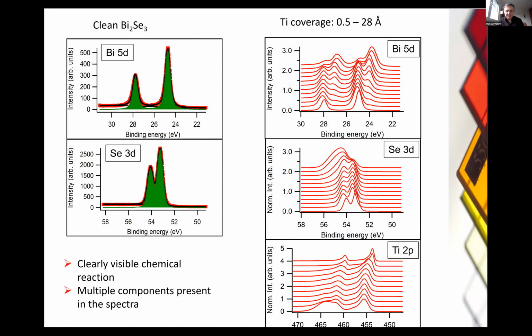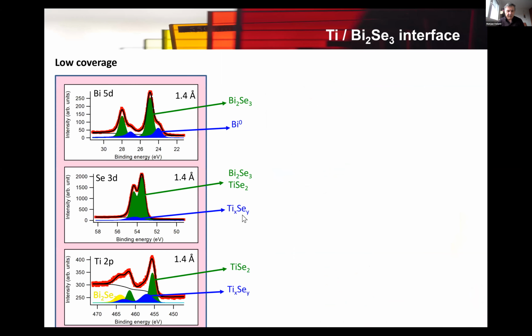So we were able to detect this interaction, and I would like to tell you that all this is done at room temperature. There is no heat treatment or anything. The deposition of titanium was done at room temperature, and all this analysis. So our next task is, of course, to understand what chemistry is going on here. So we deconvolute all these spectra to understand whether new species of these elements, new valence states, and new chemical environments around these elements appear. And it was not a difficult task to understand that we are getting metallic bismuth.